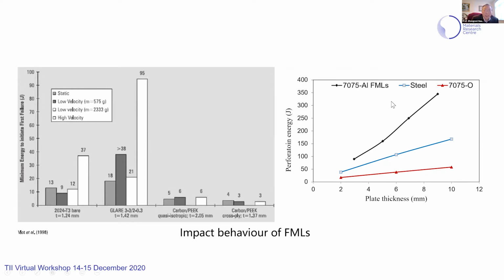On the right of this chart, I show some simulation we have done using a validated model. The black line is 7075 aluminium-based fiber metal laminates, the blue one is steel, and the red one is aluminium 7075-O. As you can see, as the plate thickness increases, the perforation energy increases significantly for fiber metal laminates, well above steel and aluminium.